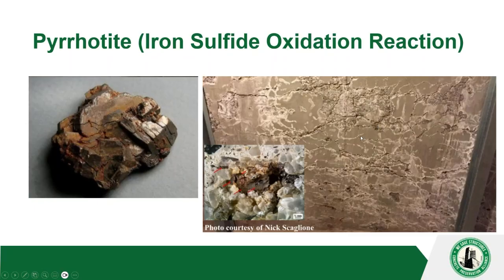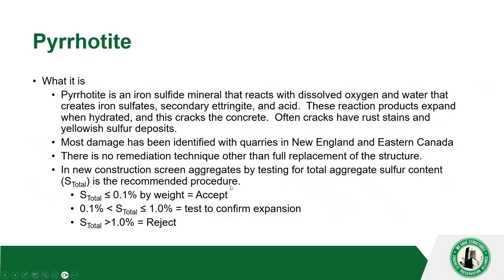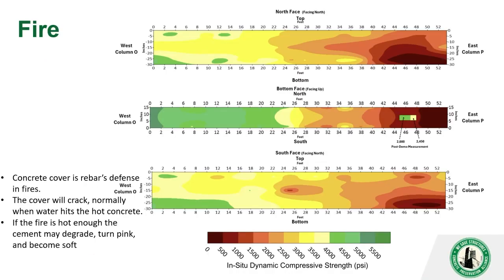There's really not a whole lot you can do other than not use that aggregate, and the key is to test for those aggregates up front. You get the total sulfur content, and if it's too high, you just don't use that aggregate. And if it's less than 0.1% by weight, you can accept it. If it's in between, then there's a few additional expansion tests to confirm whether or not the aggregate is going to react.